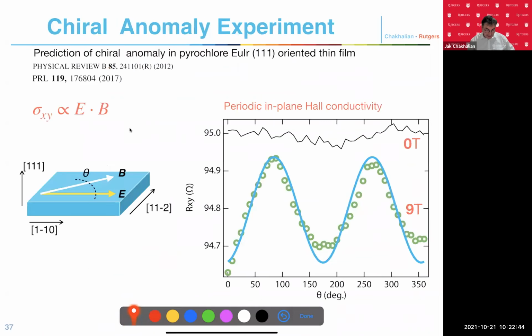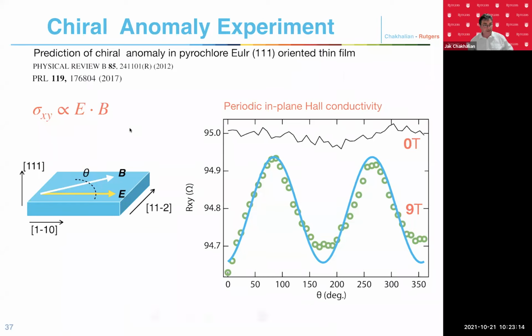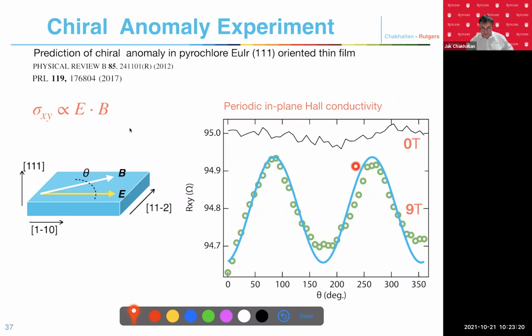Okay, so here I'm going to report, it's the first time I'm showing this graph. This is baked right out of the machine. This is the chiral anomaly in our europium-based (111) oriented thin film. This is the conductivity, I remind you, is proportional to E dot B. So what we've done, we run the current here and apply magnetic field, and we rotate the magnetic field. This is the degree. And as you can see, once the magnetic field is 9 Tesla here, you see beautiful cosine oscillations as I predicted.